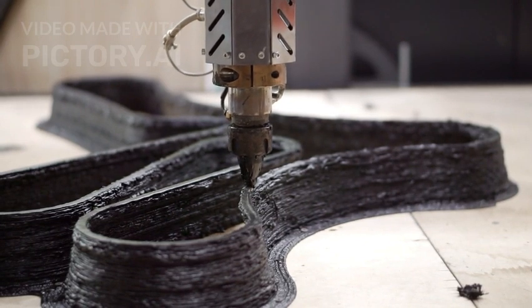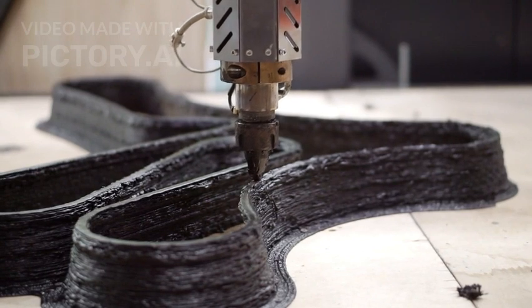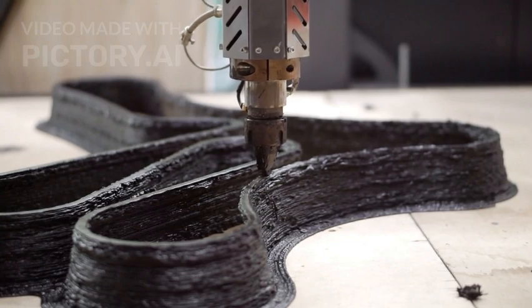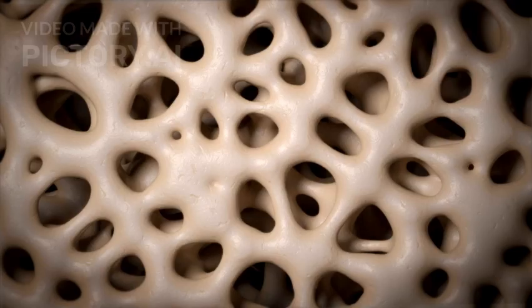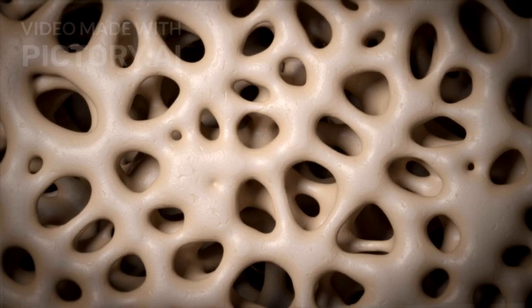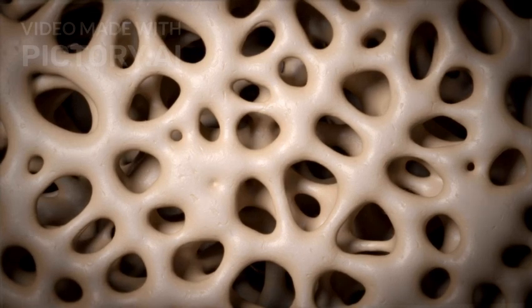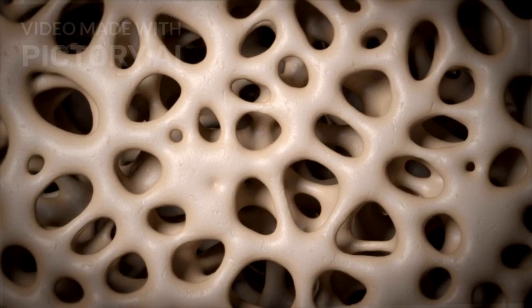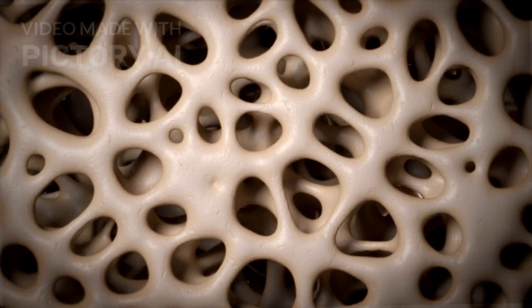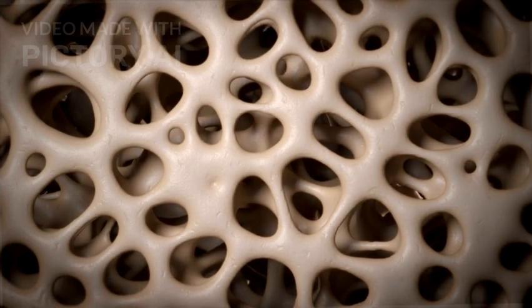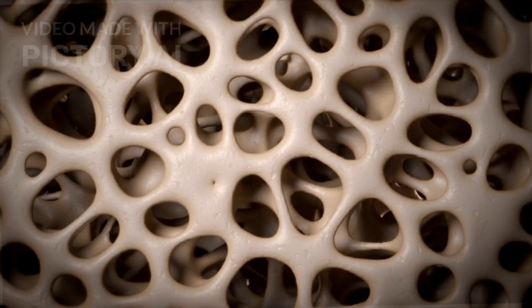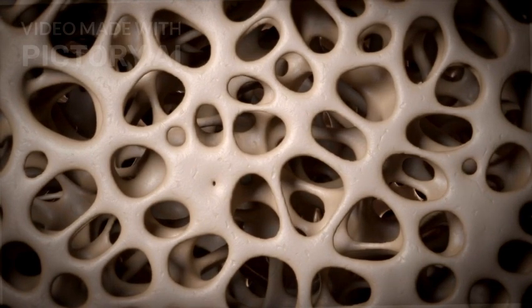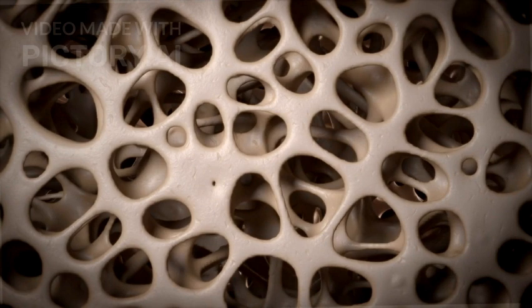Okay, that makes sense. So defect healing gives about a 3x strength increase, and it works for both PCL and PLA. But PLA gave a 6.5x increase overall. So where does that extra doubling of strength come from for PLA? Right. That brings us neatly to the second mechanism identified by the FEM analysis, stress shielding. Stress shielding. Okay, what does that mean? This mechanism does depend on the mechanical properties of the polymer itself, specifically its stiffness, its elastic modulus. Okay, so here the stiffness does matter. Absolutely. If the polymer filling the pores is itself relatively stiff, it can actually carry a portion of the applied load when the whole composite structure is compressed. It effectively shields the ceramic rods from some of the stress.